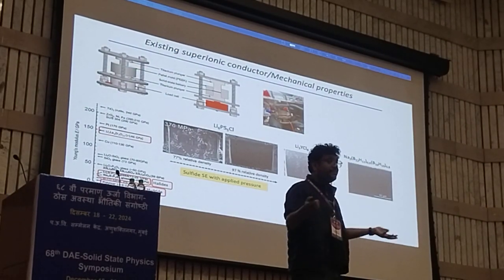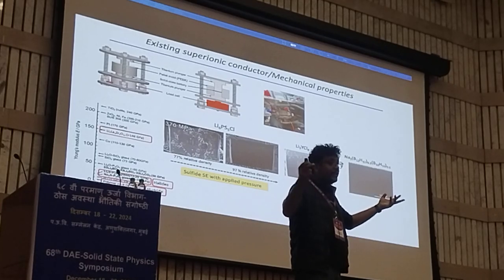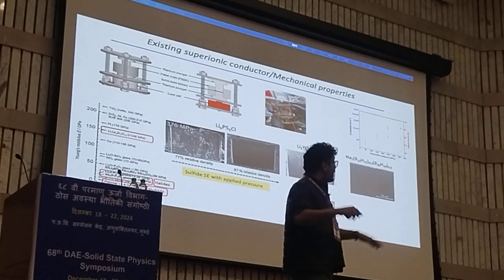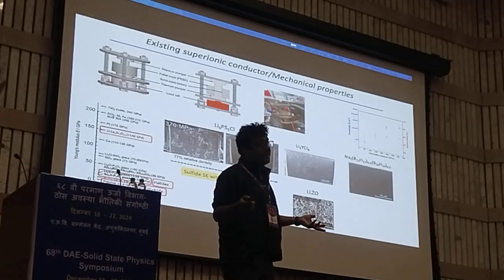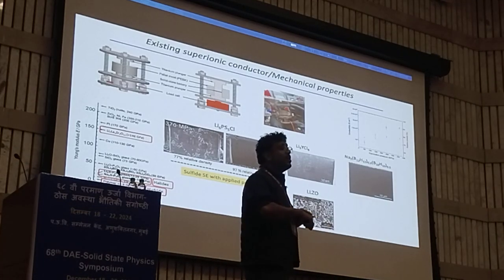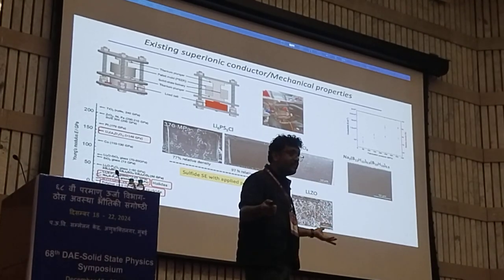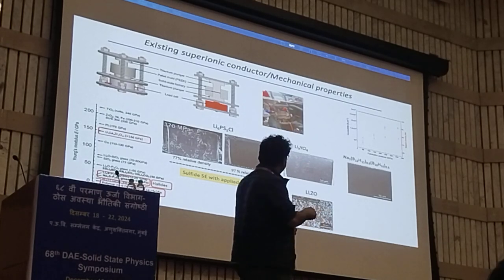Hydride electrolyte, if you densify, just becomes kind of a polymer. You really do not see any kind of grain. But oxide, if you densify, you see so many surface defects. So that is why these electrolytes are more suitable for battery application than oxide. Oxides always have a lot of grain boundary resistance, and always a lot of defects, and are very hard to densify at room temperature. That is why, on processability, these three electrolytes, hydride, halide, and sulfides, are much better.